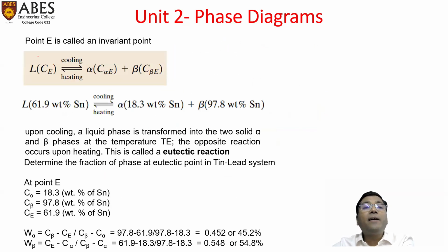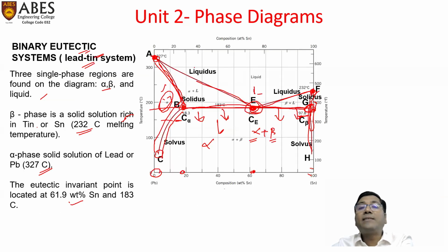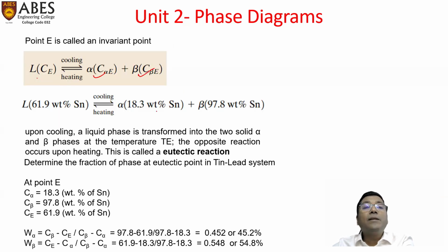And for the invariant reaction, we can write: liquid having composition Ce, when we heat or cool, will get converted at this point only into alpha of composition C alpha plus beta of composition C beta. Means liquid at Ce at this instant will convert into C alpha of 18.3 and C beta of 97.8 weight percent. L of 61.9 weight percent, in cooling, gives alpha of 18.3 weight percent and beta of 97.8 weight percent tin. Upon cooling, a liquid phase is transformed into two solid alpha and beta phases at the temperature T. The opposite reaction occurs upon heating. This is called a eutectic reaction.